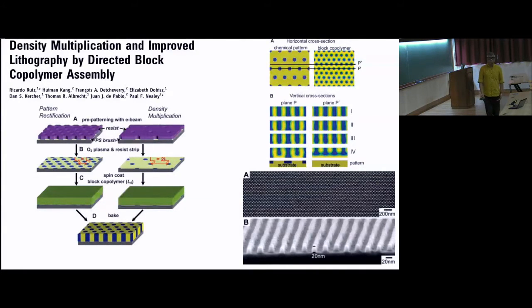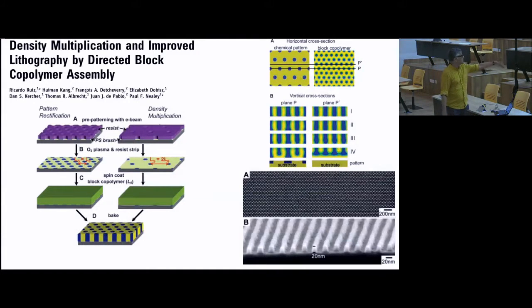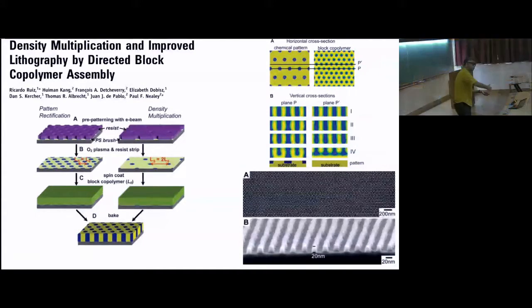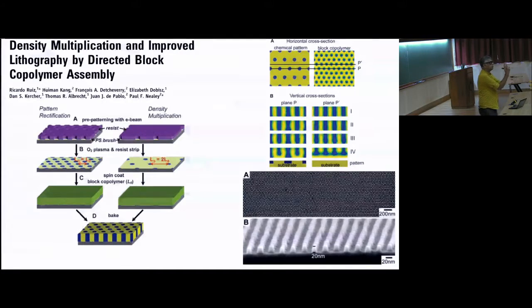The idea they came up with was to use block copolymers. You have two blocks — it's a surfactant. If you pick them just right, they will make cylinders. You put down a big pattern lithographically, say a 50 nanometer space, and onto that you coat a layer of di-block copolymer. The di-block copolymer wants to make cylinders, but the cylinder pattern width you can pick to whatever you want by choosing the two block lengths. You use the underlying mask as a template — one cylinder sits on top of the pattern cylinder, everything else follows. As long as you have an integer number of cylinders between the mask features, things completely template.